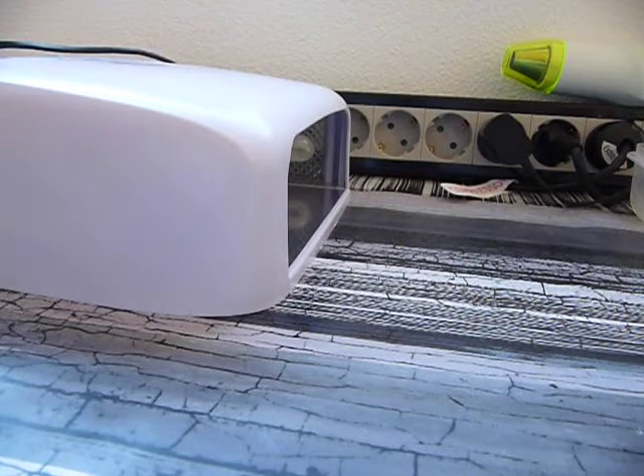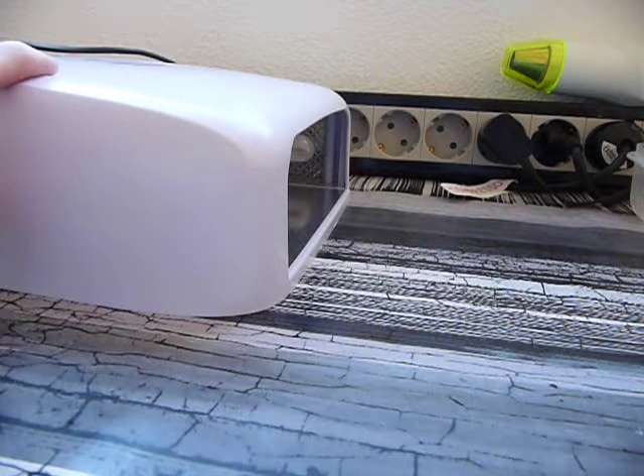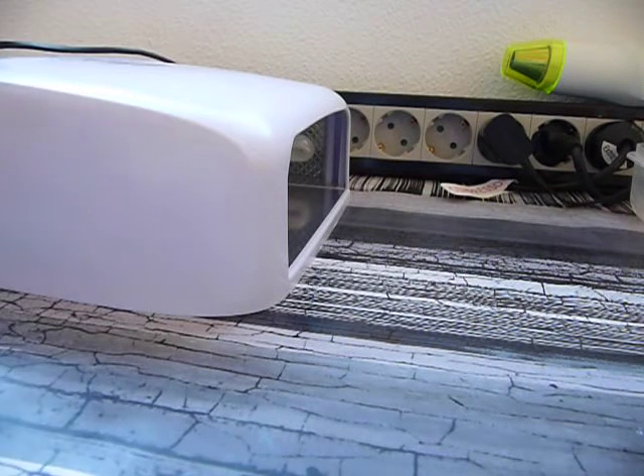For fine lines and fine text, my first cure is 27 seconds. That may seem long compared to something like the Teresa Collins stampmaker instructions, but they use different things - probably a different resin - and different resins have different times. They're also using complete black negatives, which mine may not be, and possibly different glass thickness. I can only give you the times for my particular setup.